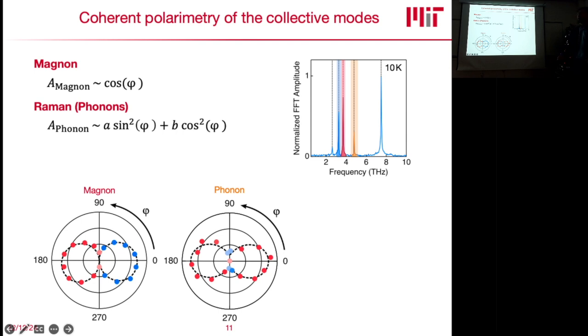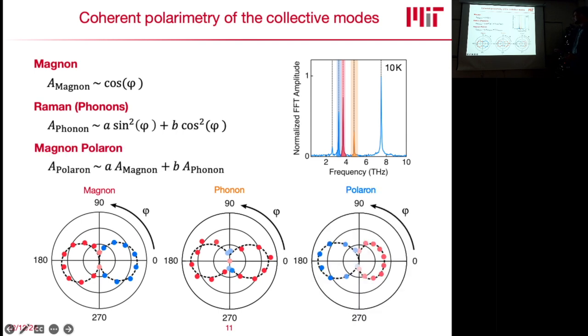So how would it look for a hybridized mode? And this is actually what we get. We get something that is a little bit squished on one side and a little bit elongated on the other side. And this is actually due to this aforementioned interference between this positive lobe here, which gives us an elongated positive lobe here, or in that case, negative lobe. And so this negative lobe here destructively interferes with this positive lobe, and therefore it is a little bit suppressed. And so if we carried out this excitation field dependence on this side where it's suppressed, where they're destructively interfering, and then did the same experiment on the other side, which we did, you actually see an upturn in the excitation field dependence. So this gives us confidence that we can very much pick up this hybridization of these modes and this spin-lattice coupling in our experiments.